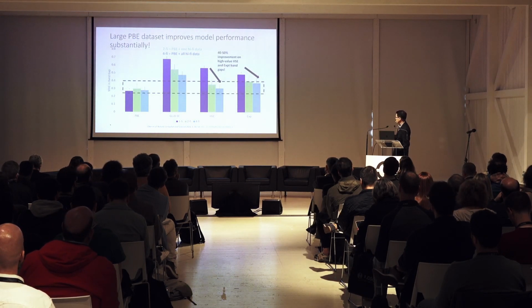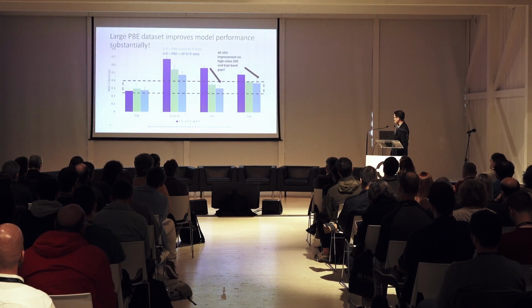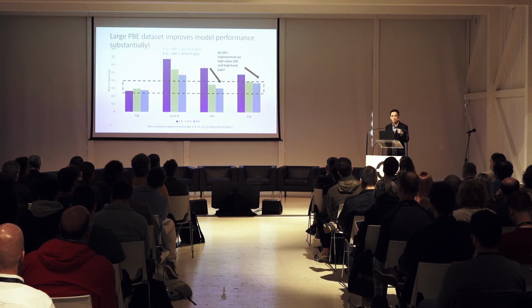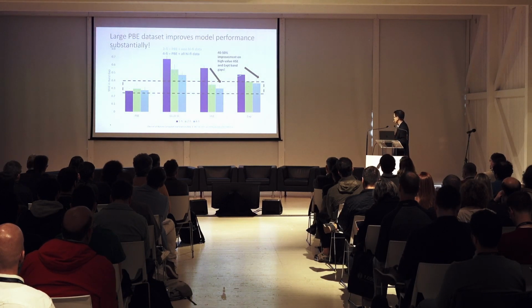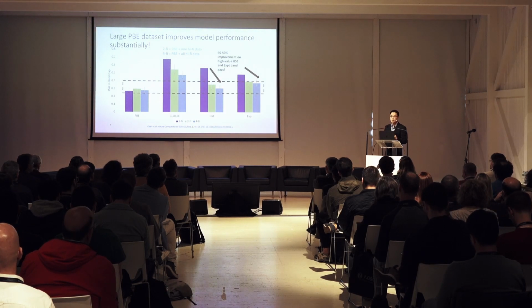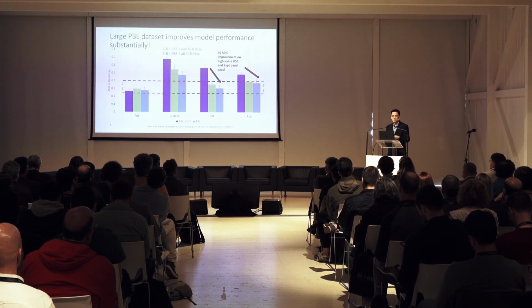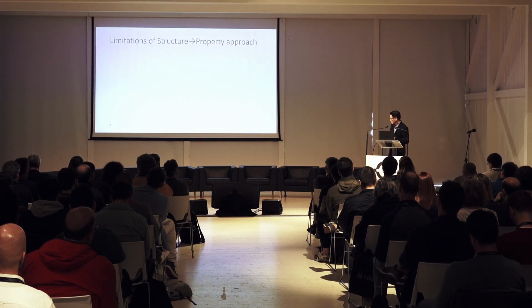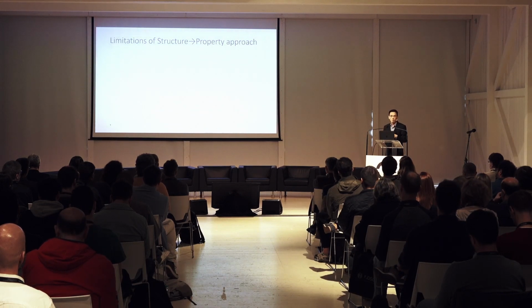However, if you build the multi-fidelity model that I just talked about, just by incorporating the PBE data as a low fidelity data set, you can actually get a 40 to 50% improvement in your predictions of the high value HSE and experimental band gap data. Okay? So in other words, we are essentially getting much better performance on the ML model just by relying on chemistry and structural latent features that were learned using the large PBE data set. Okay? Alright.